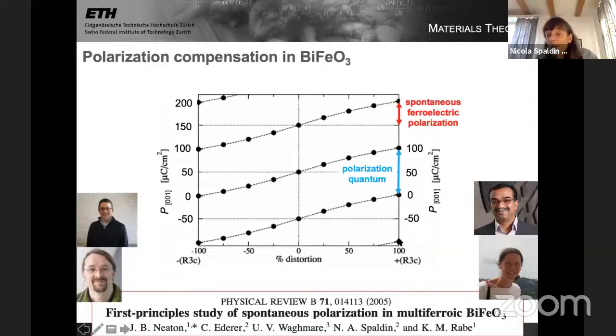So now if I look at the polarization of ferroelectric bismuth ferrite, you see that one of the allowed values is 0. And likewise, if I switch into the other direction, one of the allowed values for the polarization of bismuth ferrite is 0. So we have this very strongly ferroelectric material, which actually can have a polarization of 0, which seems a little bit counterintuitive.